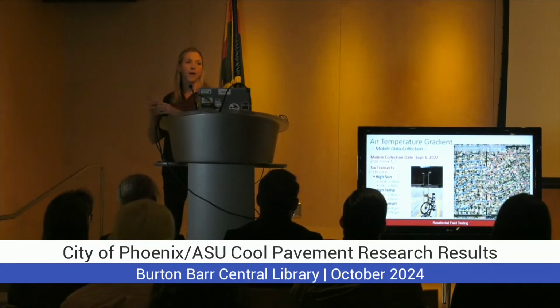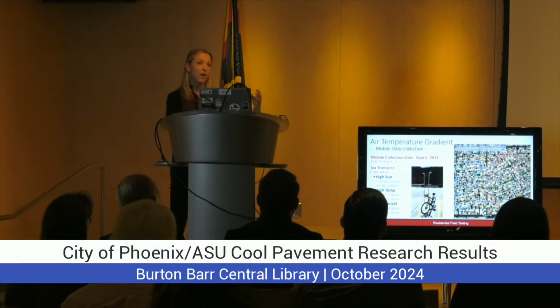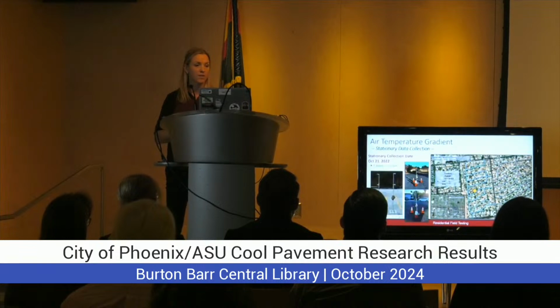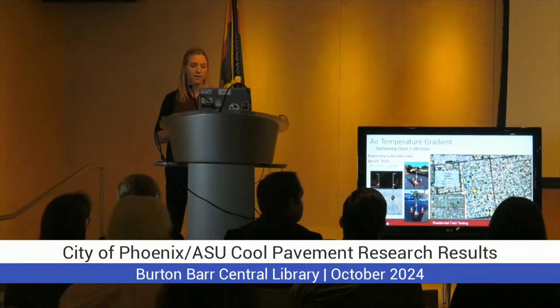But we were able to just compare what the temperatures are in the cool sealed part of the neighborhood versus over the asphalt part of the neighborhood with this. And then we also did the stationary data collection where we put these sensors, at the same heights, in the cool seal part and the asphalt part.